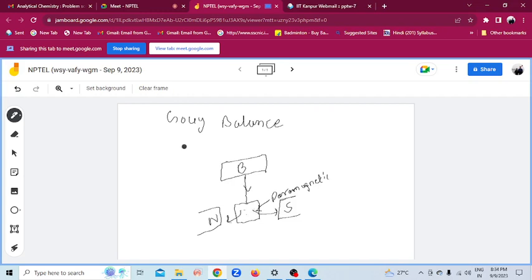So it will be pulled like that, and in your balance there is a mass gain. The mass of this sample will increase. It will show that the mass is increasing, but it is actually due to the attraction of the paramagnetic sample to the magnetic field.